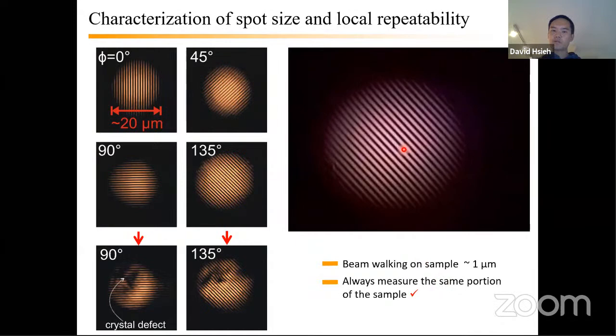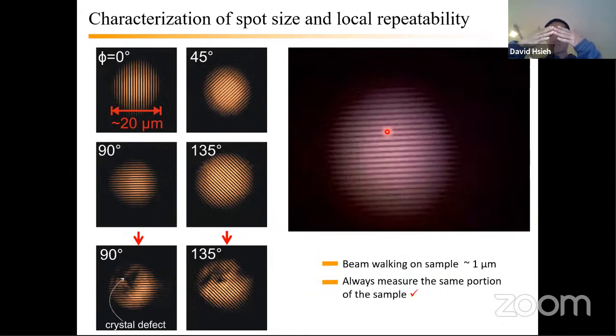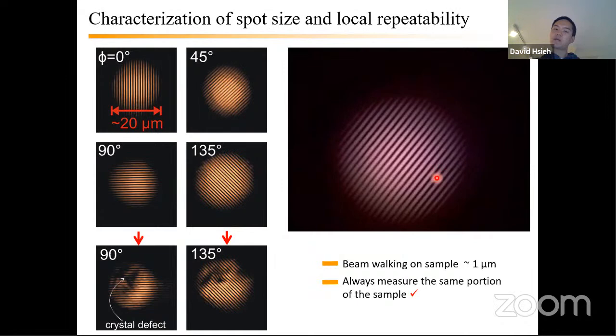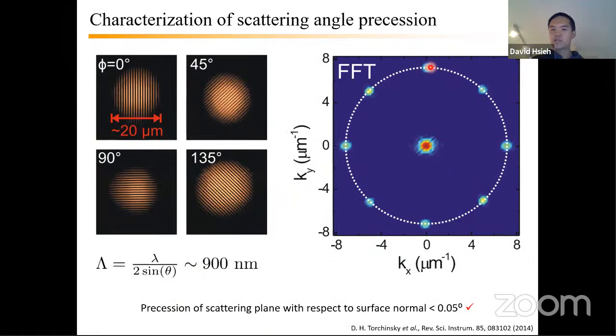And moreover, with this sort of grating type technique, you can quantify how much your angle of incidence is walking as you rotate your scattering plane just by comparing the K vector of this grating at various scattering plane angles. So here I'm projecting that K vector at select points along my phi axis. And again, the precession of our scattering plane is pretty good.